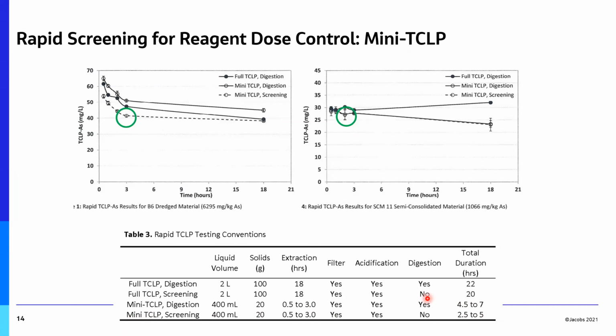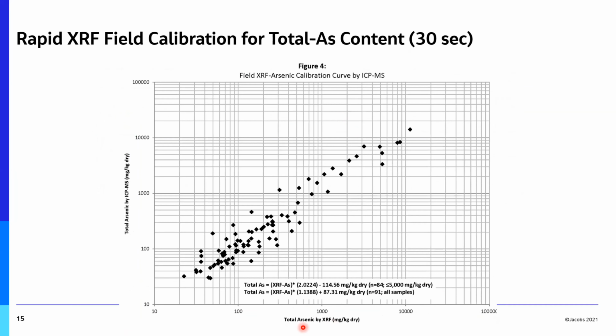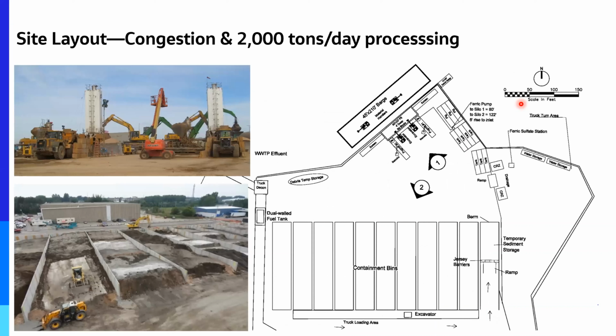For the XRF, we took a handheld device and calibrated that against the totals by the official procedure, and we came up with a calibration line. So now we're in the position where we know what the leachability is, we know what the total is, and this helps us, in addition with moisture content data, to figure out whether we have soft DM or semi-consolidated material, and we can begin dialing in or ratcheting down our dose to make things more cost effective.